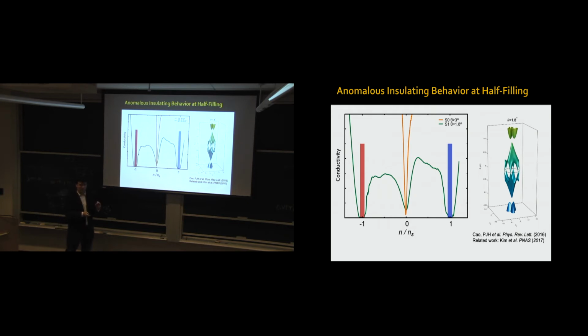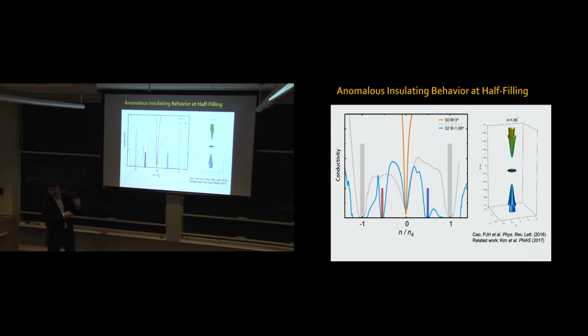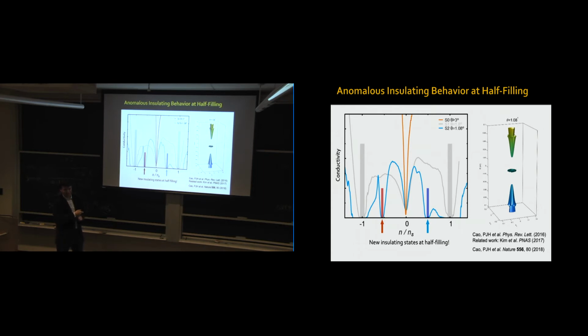Let me show you now what happens if we take a device with a magic angle, 1.08 degrees. Near charge neutrality, I still have sort of graphene Dirac cones, so I have this V-shaped conductivity. At full filling or full emptying of the superlattice, I have also zero conductivity. But now, halfway through, when I put half as many electrons as I could in this band, or half as many holes as I could, I get an insulating state. The system should be a metal, but it's not a metal, it's an insulator.